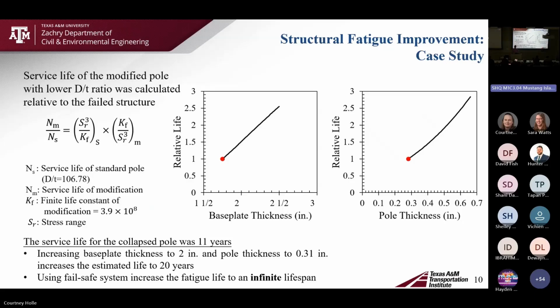So using the relative life equations in the previous presentation, we did some investigation. And we found that if you were to increase the base plate thickness only by 1/4 of an inch to a 2-inch base plate thickness, and increase the thickness of the pole by just one size to 0.31 inches, you would nearly double the estimated life of the pole. Where it failed after 11 years, we estimate that you might have gotten 20 years of life out of it. So it's a relatively simple solution, just changing some existing parameters that can have a pretty large effect.